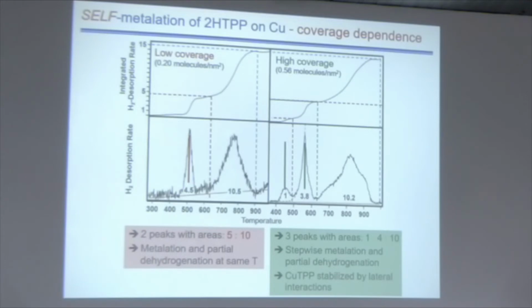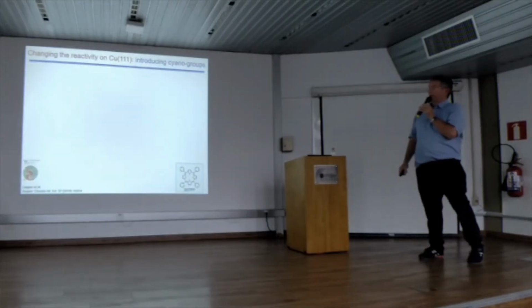And how do we find out? It's very simple. You just integrate the spectrum, and this is shown here. You integrate the spectrum, the first signal increase, then you integrate, you have another increase, and then you have another increase, and then you say at the end of the day, I have 16 hydrogen molecules in my molecule, 15, sorry. And this gives me the scale up here, and then if I look at the scale, I see that this is 1 and this is 4. So exactly in line with what we proposed from STM. Okay.